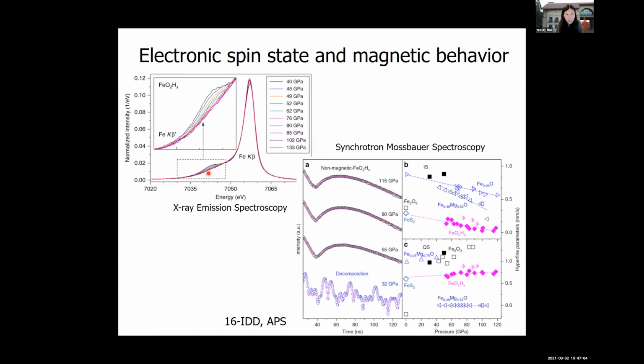And we also heard about synchrotron Mossbauer spectroscopy. So we collected a series of SMS spectra on the FeO2H compound, and it showed that it's non-magnetic for all the conditions under which it's stable. And you get a single clean single-peak spectrum, regardless of the content of hydrogen in the lattice. We also analyzed these spectra using the CONUSS program to extract the quadrupole splitting and isomer shift of the iron in FeO2H. And I guess I would just say the values of the QS and IS of iron in this FeO2H material, when extrapolated back to ambient conditions, are very close to pyrite.